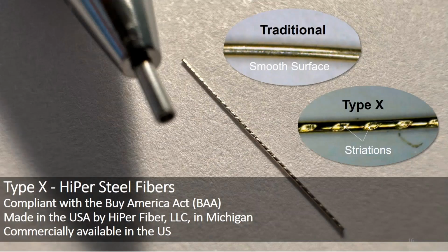Now, the reason this was funded is because of the type of fibers that are available. HiPer Fiber makes these striated fibers. Basically, the fiber surface has striations in them. They are just microns deep and microns wide, and you can barely see them. In most cases, you cannot see them unless under certain light conditions. These fibers are compliant with the Buy America Act. They are made in the US and they're commercially available in the US.